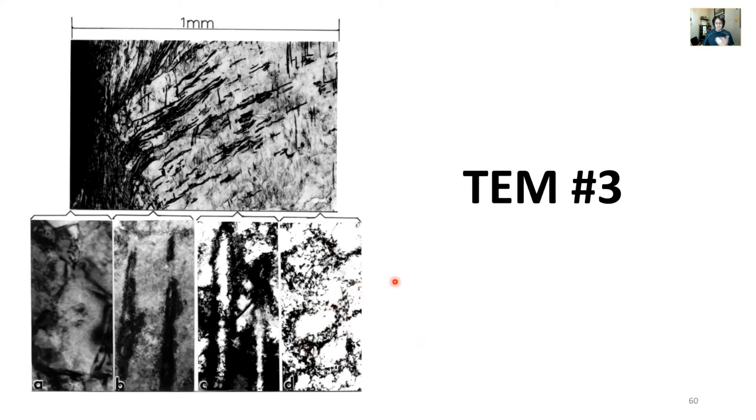And dislocation cells are kind of like grains, actually, and they do contribute to the strength of a material. So you can modify the Hall-Petch equation and add a term for dislocation cell diameter and estimate the effect of the presence of these dislocations or dislocation cells on the overall yield strength. It's a very interesting phenomenon.